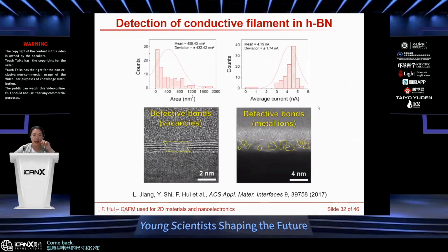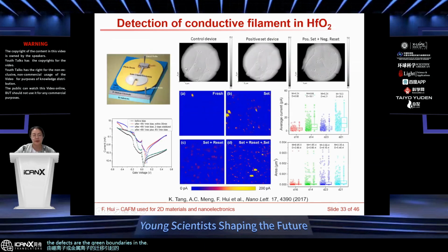Combining with cross-section TEM, we can conclude the resistive mechanism, which is caused by the migration of boron ions or metallic ions, which cross through the defects or the grain boundaries in the switching layer. This strategy is also feasible for detecting conductive filaments in different materials.